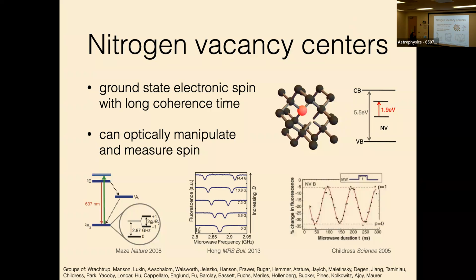And there's also a very convenient mechanism for optically manipulating and measuring the spin, basically just using a laser that is not very much more sophisticated than this green laser pointer. You can just shine light on the defect and spin polarize selectively into one of your spin sublevels. And there's also a mechanism for reading out the spin resonance optically. If you start in this ms equals 0 spin sublevel, I can just scatter photons and cycle back and forth. But if I start in one of these other spin sublevels, there's a spin-dependent inter-system crossing to a dark state.